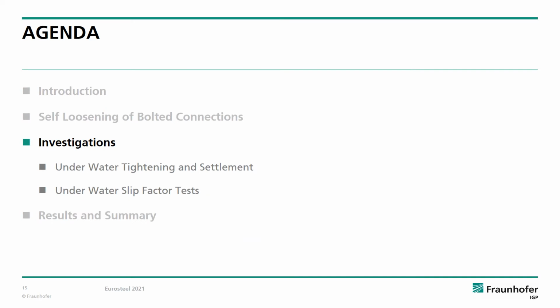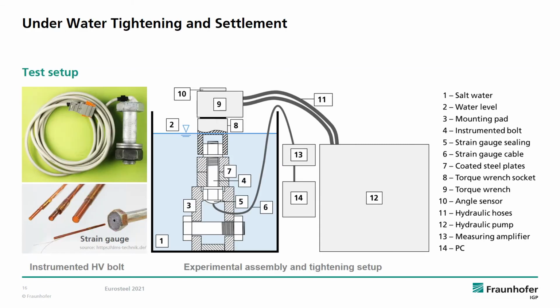We did a lot of underwater tightening and settlement tests, and we also developed a setup to perform regular slip factor tests underwater. For our tightening and settlement tests, we instrumented HV bolts of size M27 and M36 by the application of strain gauges in the middle of the bolt to measure bolt preload. We put them in a box full of salt water, assembled two flange plates with a thickness of 30 mm each, and finally tightened the connection underwater.